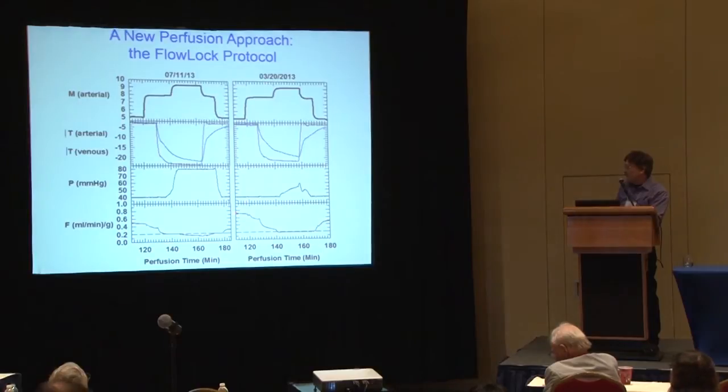So we developed this protocol in which as the viscosity increases due to increased concentration of cryoprotectant and the decreased temperature, normally the kidney flow rate drops down. And if we left this with our normal protocol, the flow rates would go to very low levels right when we need to be perfusing the kidney the most in order to get the M22 in. But we prevent that flow from dropping down. So we lock in a flow rate of 0.2 milliliter per gram per minute.